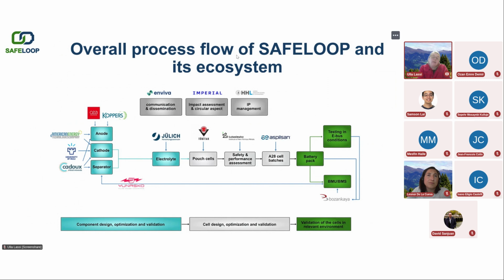Anode materials are mostly made on recycled carbon materials, carbon precursors. Not only recycled graphite, but also different carbon residues, which are used as a conductive agent material in our electrode materials. Cathode chemistry is NMC 88.